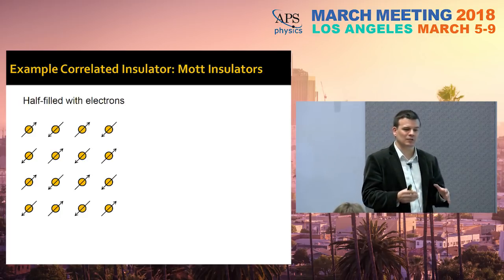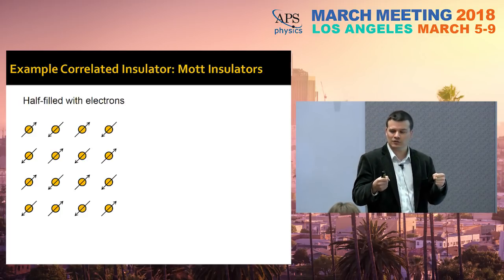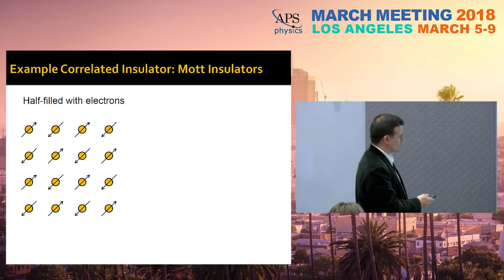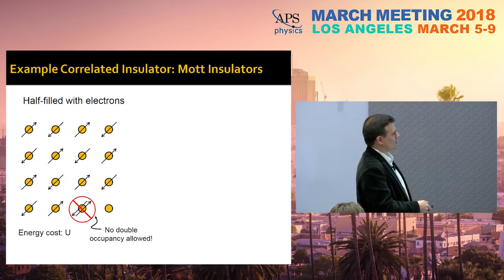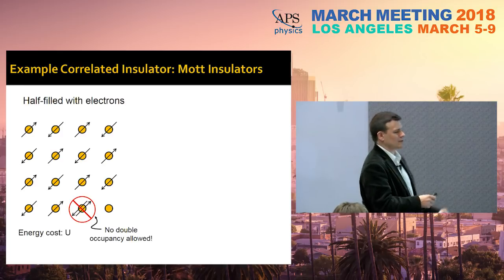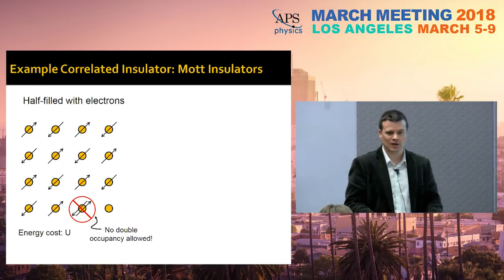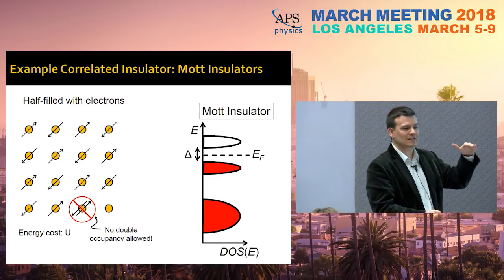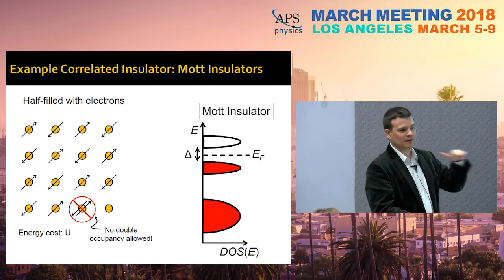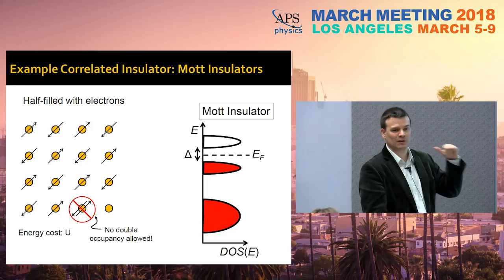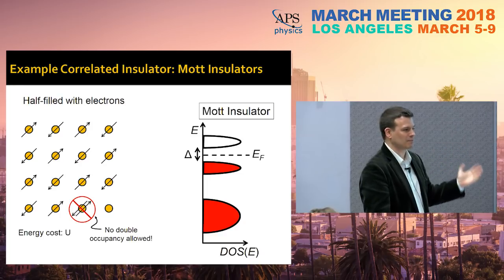However, there are materials where the interactions between these electrons are very strong, repulsive interactions. So this process is actually not allowed. You don't have this double occupancy allowed. That means that all of the electrons remain stuck in their positions because they cannot jump from atom to atom. And that forms this correlated insulator. It occurs precisely when you've half filled your band, when you put half the total amount of electrons that you could put in a band, then this insulating state appears, and it's kind of unusual.